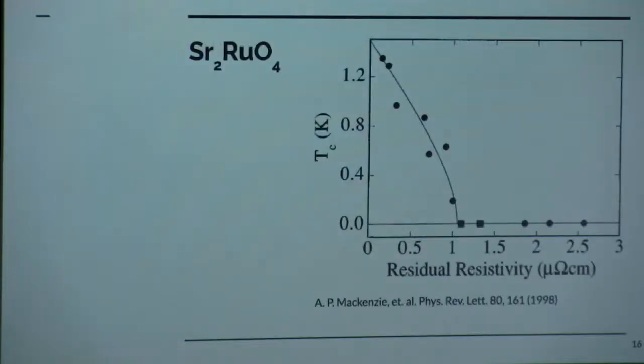One example is strontium ruthenate, which is of course a complex material, and the order parameter is debated. But here I show a well-known plot. On the vertical axis is Tc, on the horizontal axis is residual resistivity, and residual resistivity is usually proportional to the amount of impurities in the material. So you see that the impurities quickly obliterate the superconducting state in strontium ruthenate. Because of this, it's very, very likely that the superconducting state here is unconventional.